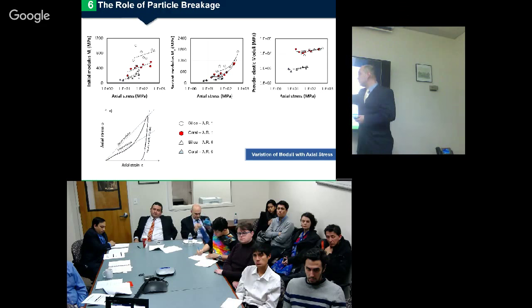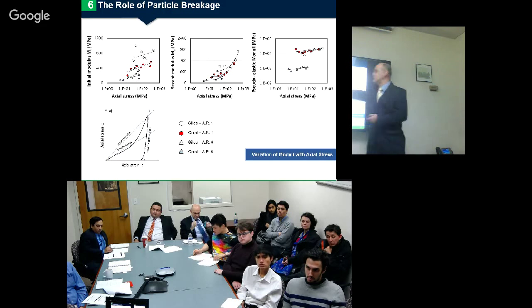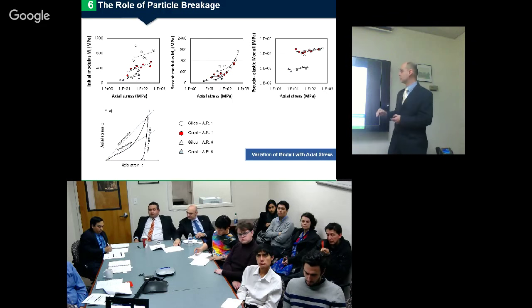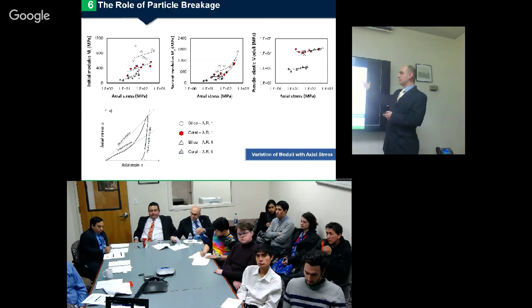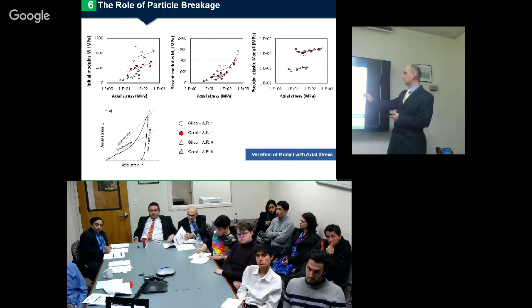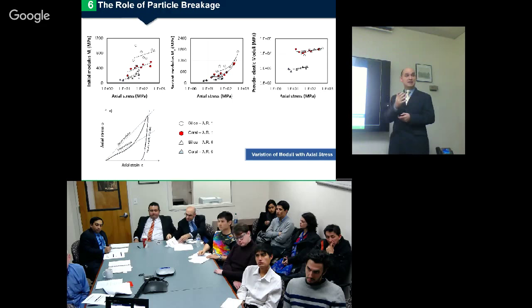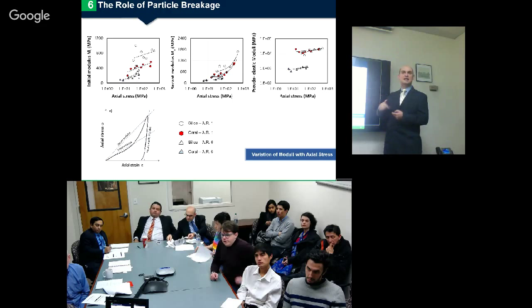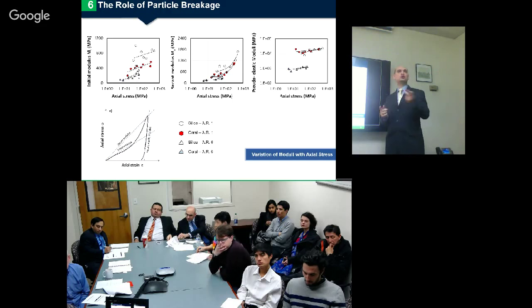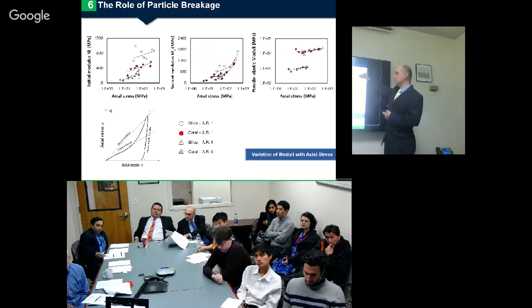Whereas for these two, the small triangle ones, which is aspect ratio of 6, the secant modulus is typically flat or horizontal. And the pseudoelastic moduli also showed us that there is a main distinction between the materials that are loaded in those two different aspects. These two small samples and these two large samples.